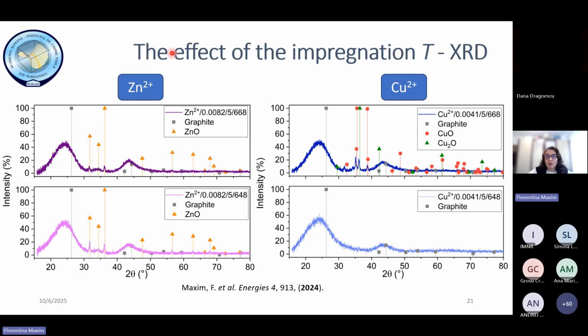So we studied the effect of the impregnation temperature, and here are presented X-ray diffraction patterns for zinc oxide deposited on carbon support and copper oxide deposited on carbon support. What is very important to note here is that the position of the zinc oxide is independent of the temperature, so either the water is in the gas-like state or liquid-like state. But in the case of the copper oxides, they were produced only in the gas-like state of the water and not in the liquid-like state.